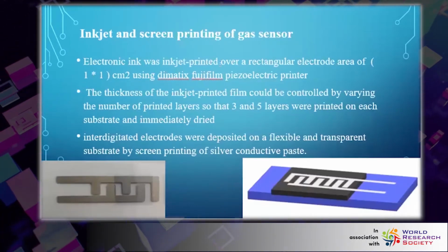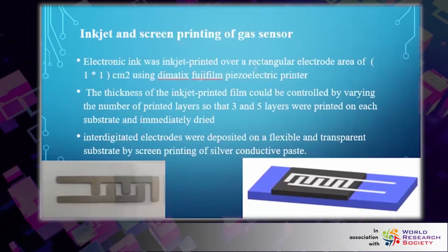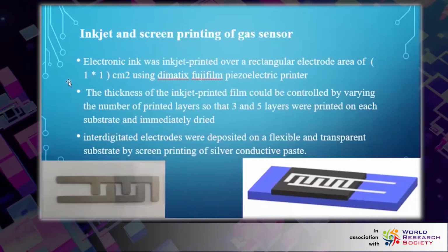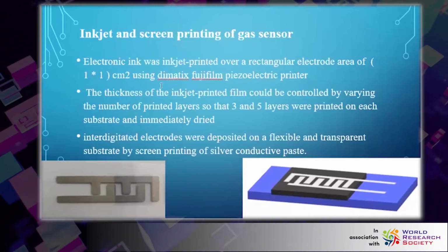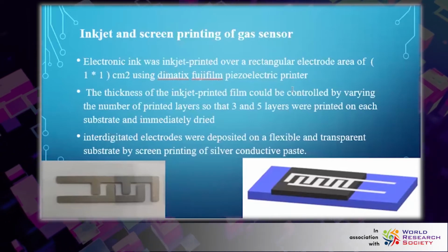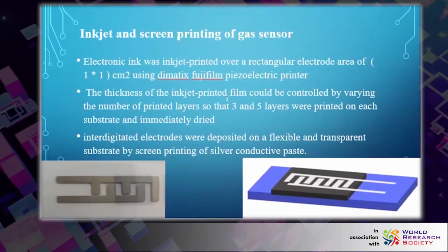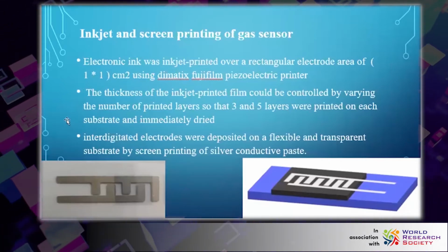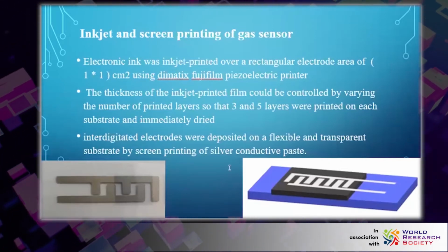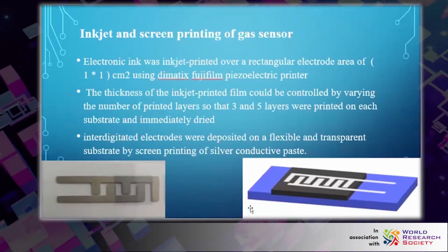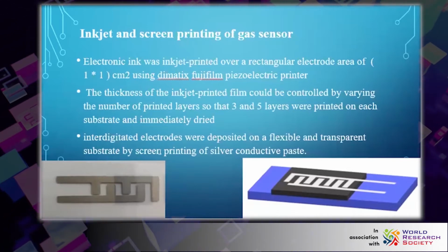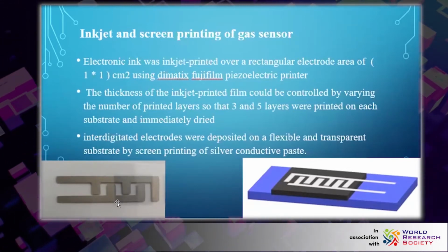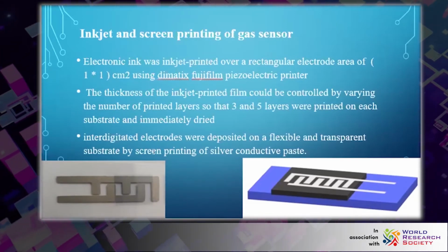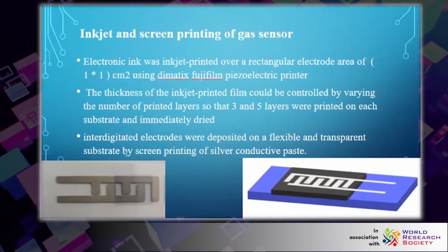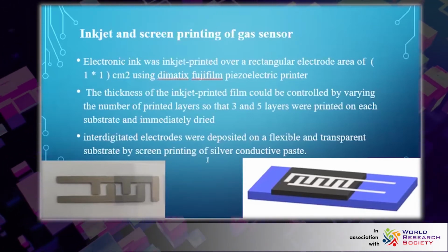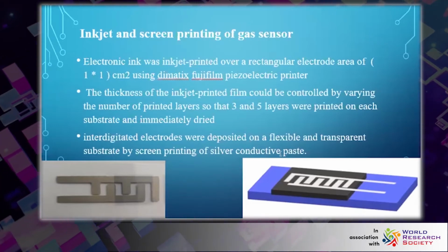Inkjet and screen printing. The electronic ink was inkjet printed over a rectangular electrode area of 1 square centimeter using a Dimatix Fujifilm piezoelectric printer. The thickness of the inkjet printed film could be controlled by varying the number of printed layers, so 3 and 5 layers were printed on each substrate and immediately dried. This is the actual picture of the sensor. Interdigitated electrodes were deposited on a flexible and transparent substrate using screen printing techniques with silver conductive paste.